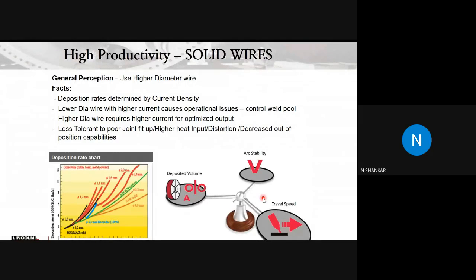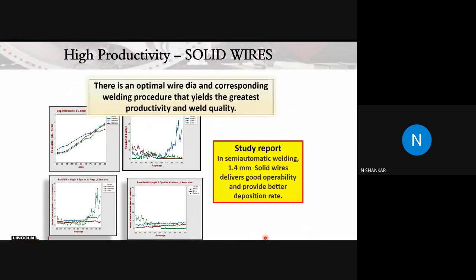So increasing the current alone will not help, increasing the wire diameter will not help. We have done a study in our Lincoln Weld lab to see what the effects are of increasing current, voltage, travel speed and wire feed speed on a process and see how stable it is. We found out that until a certain current, it's better to use a 1 mm or 1.2 mm wire. When you cross a transition level, it's better to move to a 1.4 mm wire.